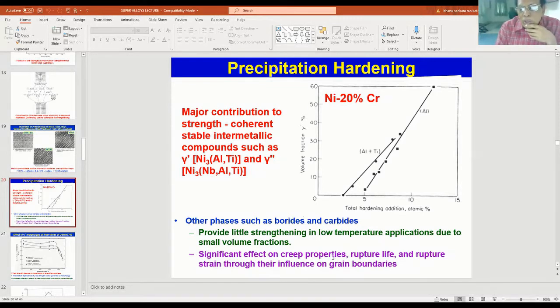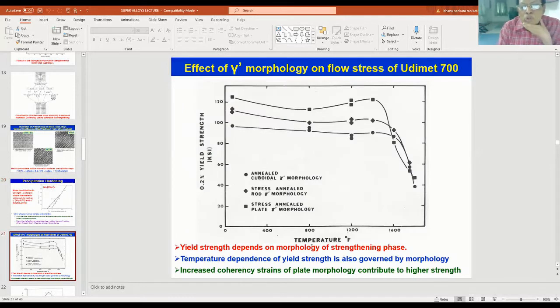They have a significant effect on creep properties, rupture life, and rupture strain through their influence on grain boundaries. The carbides contribute to the creep resistance, as already explained to you, at elevated temperatures. The role of carbides at low temperatures is very limited, and the gamma prime and gamma double prime are the major strengthening phases. I have shown you the morphology of the gamma prime that is forming.